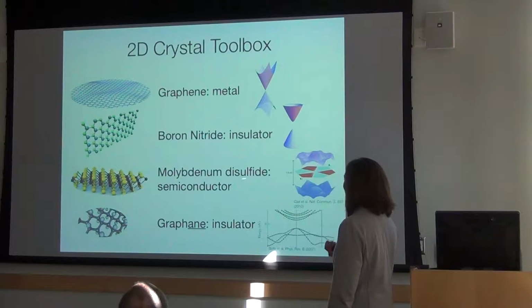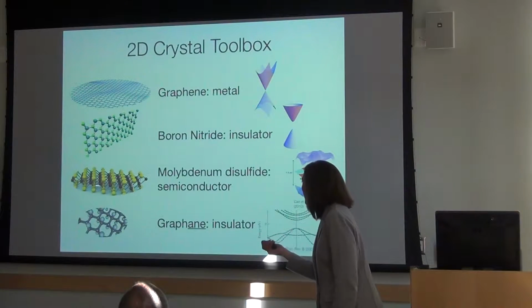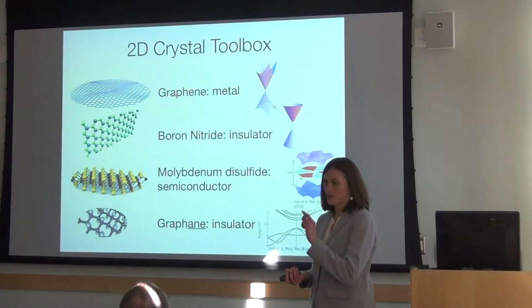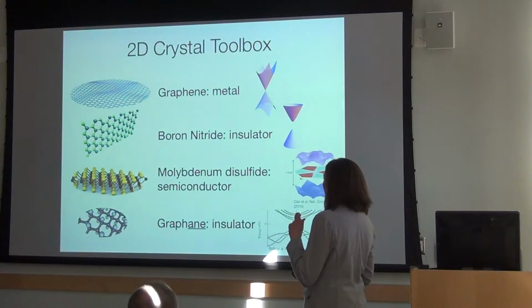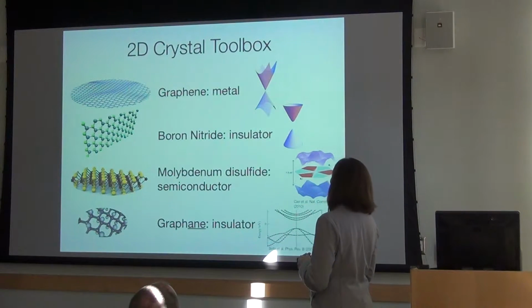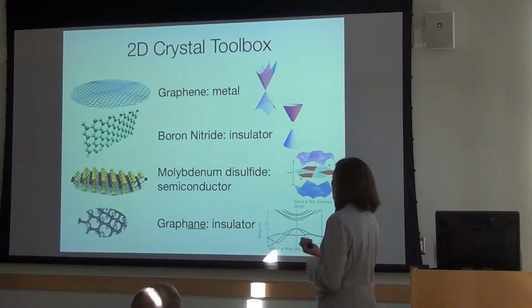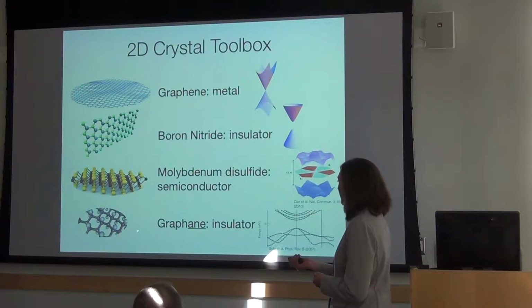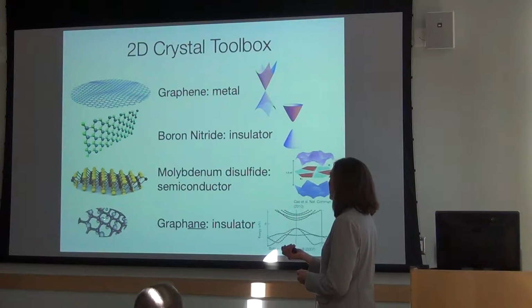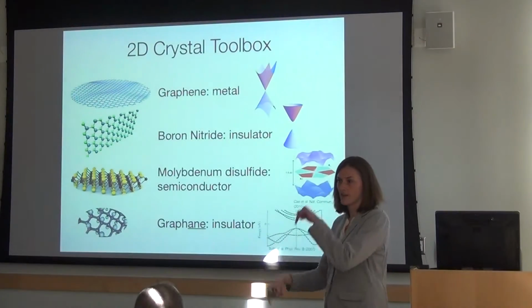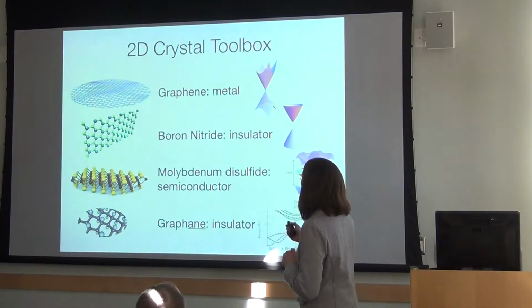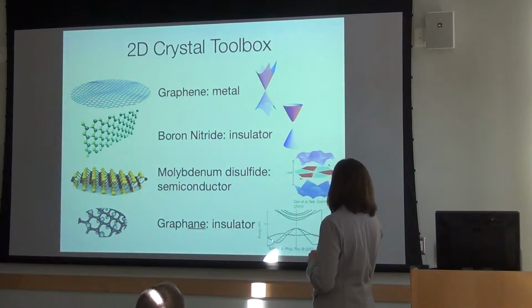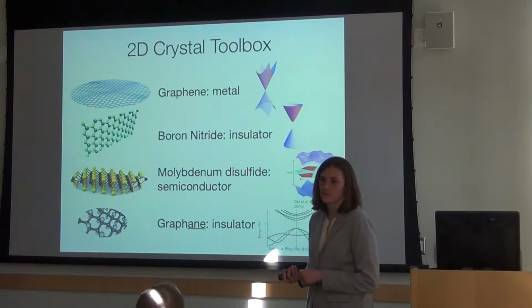And then there's molybdenum disulfide, and now we are looking at a single unit cell rather than a single atomic thickness. But it still behaves like a two-dimensional material. And this is a pretty good semiconductor. And then I'm going to mention graphane is another type of insulator because I'm going to be talking about it later. So graphane is graphene, except you now have hydrogen atoms bonded on each of the carbon atoms in an alternating up and down pattern. And this makes graphene, which was a good metal, into a pretty good insulator.